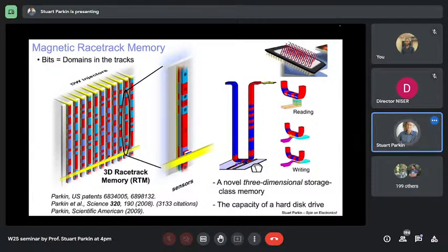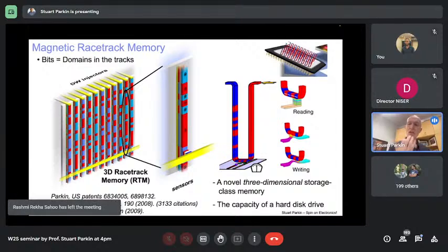And my concept was that if you pass a current through this nanowire, which is homogeneous, all of these domain walls would move synchronously around the racetrack. And therefore, we could move the data to reading and writing devices. So this is a very interesting concept that I thought, because it's totally unlike any other memory technology at that time, which was 20 years ago, and even today. It's the only one in which you move the information around the memory device. And therefore, in one device, we can store 100 or hundreds of bits.